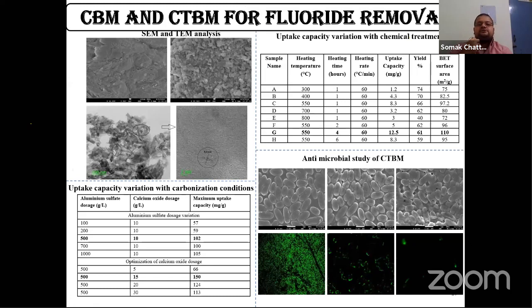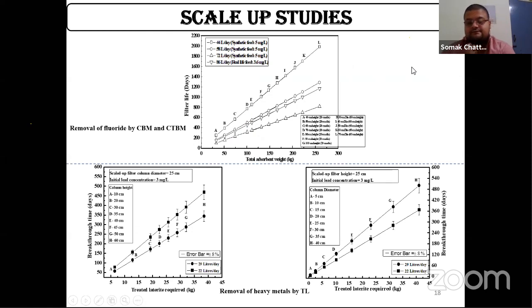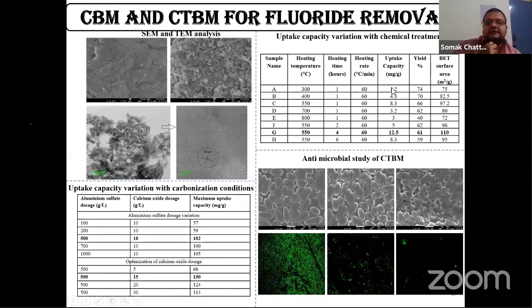Now coming to the carbonized bone meal and chemically treated carbonized bone meal for fluoride removal. The first thing that we did was optimization of the carbonization condition. Initially we varied the heating temperature, and our main aim was to find out the fluoride uptake capacity and the BET surface area. Once we increased the heating temperature from 300 to 550, 700, or 800 degrees Celsius, we saw a rough variation in the fluoride uptake capacity. This was our major concern. If we increase the fluoride uptake capacity, then we can fix that value of temperature. If we go from 300 to 550 degrees Celsius, the uptake capacity was increasing from 1.2 to 8.3.